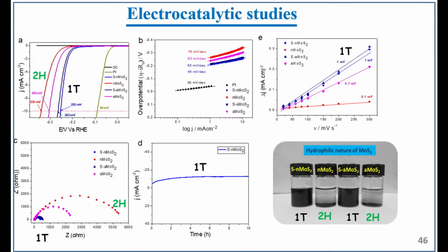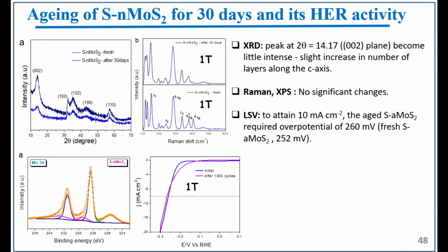This is directly related to the electrochemical surface area, which is measured from the non-Faradaic region, where you can see that the 1T phase, due to its hydrophilic nature, has a large surface area, almost 10 times higher than 2H. Similarly, you can see that the Rct value is less than 1000 for 1T, but close to 6000 for 2H. So the conductivity is diminished in the case of 2H, because 1T is purely metallic. And then the best material, S-nMoS2, sustains the 10 milliampere current density over 10 hours of long-term operation without any deviation. The hydrophilicity also shows that the 1T cases are more hydrophilic and 2H are more hydrophobic. So this is the best activity, and we have also seen the stability.